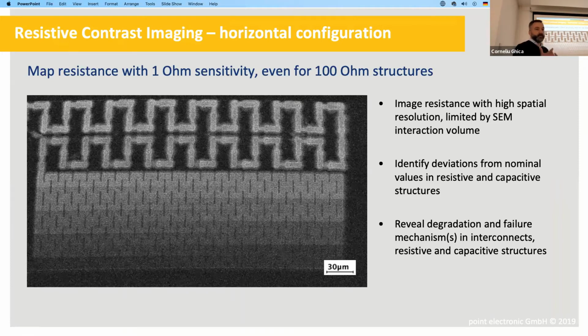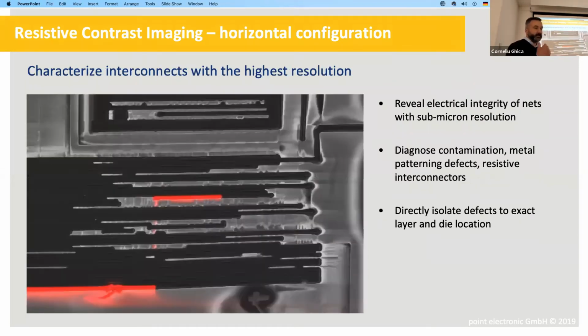You can go back and check, is my resistor uniform? How uniform is it? And if it's not, which of the segments is not uniform? And then you can make a cross section and prepare a TEM lamella. The most typical use is what the images that I'm showing here. You have a network, so we're looking down onto a CMOS chip that's been unpackaged and delayered, so we can probe it with the electron beam. And we're looking down onto it, and we want to know how everything is connected.